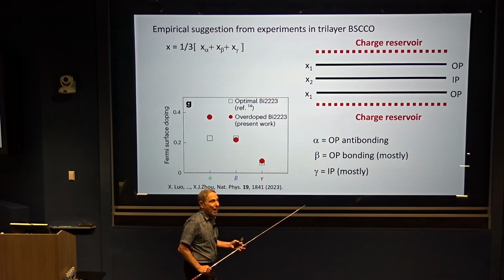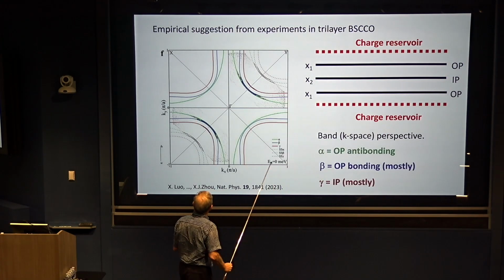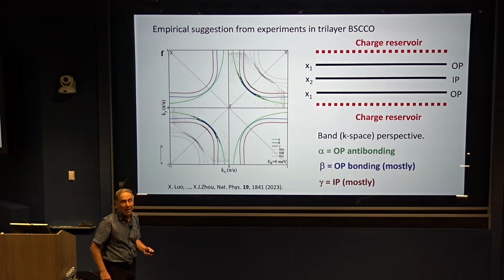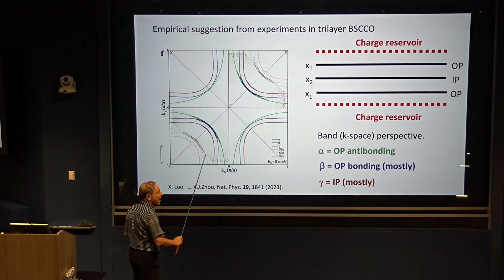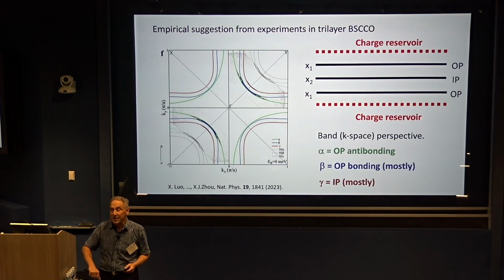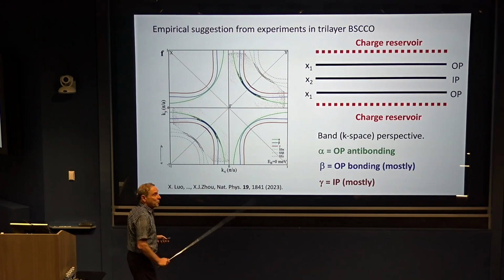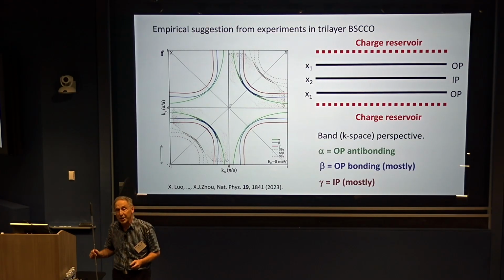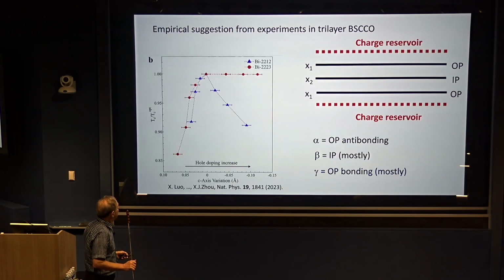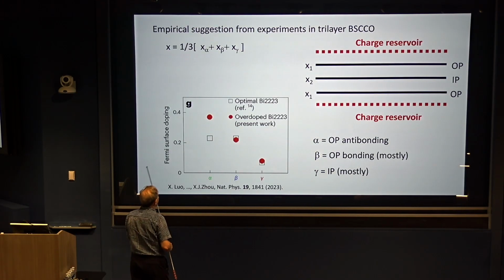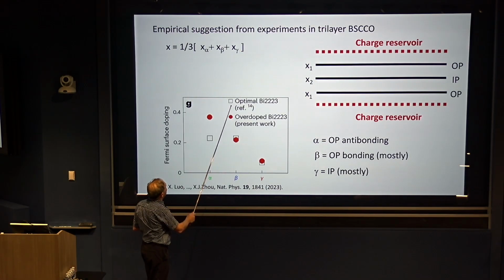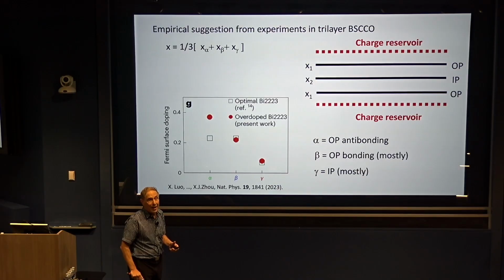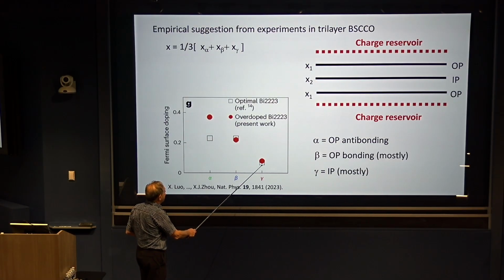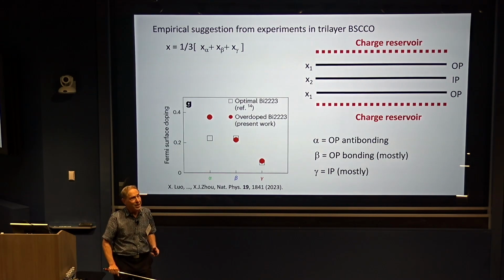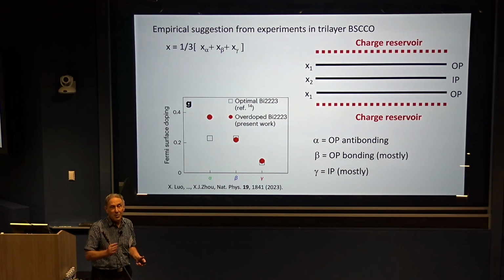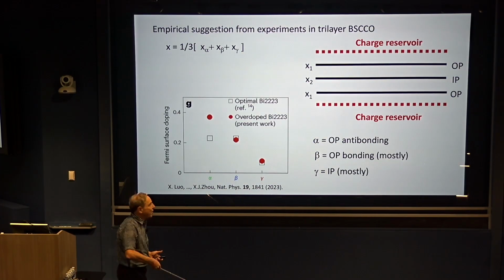Okay. So going back to this picture, this is an ARPES picture. And what you can see from ARPES is you can estimate the area enclosed by the Fermi surface. So we don't have to guess. We can tell what is the doped hole concentration in each of these bands. And that's what's plotted here. So this is for two different samples. The squares are for optimally doped trilayer BSCCO. And so what you can see is that the gamma band has an extremely low concentration. It's about 6%. So by itself, this would have a TC that was near 0 because it's too underdoped.